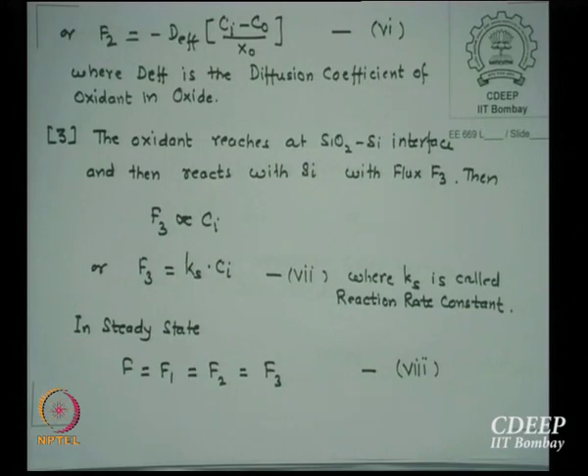Oxidant is now diffusing. Please remember the process we are describing. From the gas phase, oxygen is coming. Equivalently it gets to the silicon oxide surface, then diffuses through and then reacts with silicon to form fresh oxide. Is that clear? That's what the Deal-Grove model is suggesting. Gas phase through oxide and to react with silicon. That's the process we have defined.